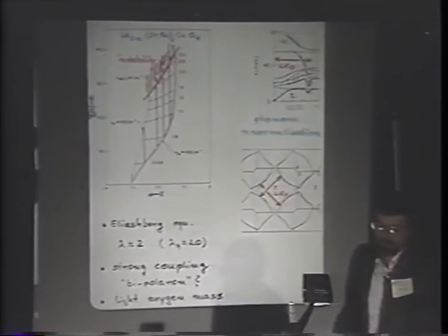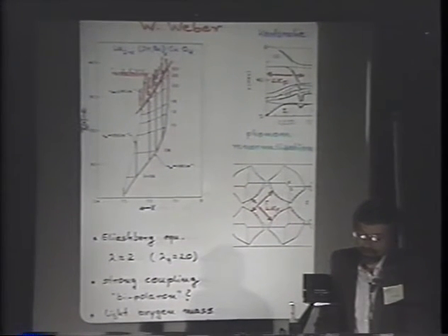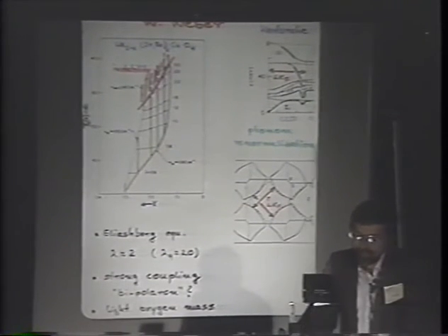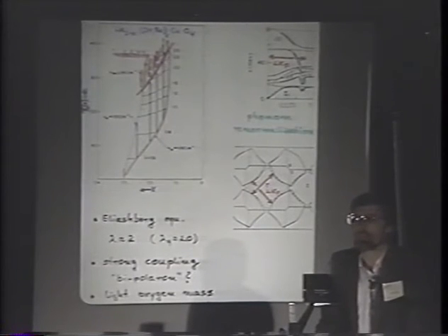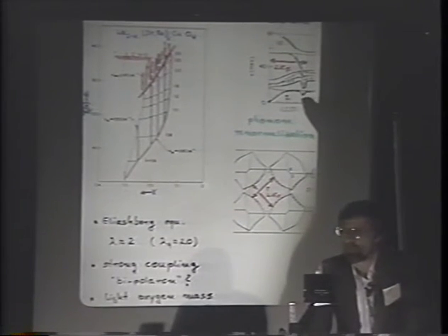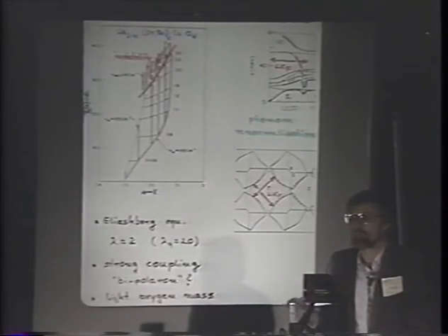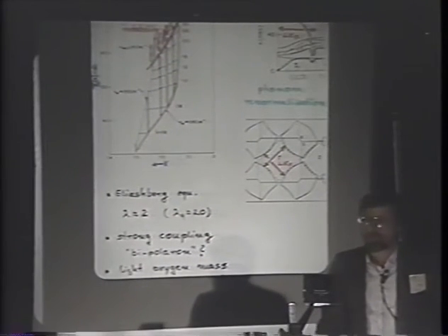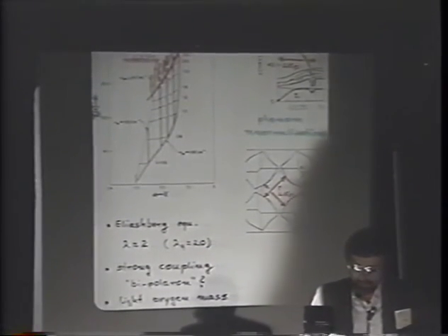Weber is calculating at the moment the electron-phonon coupling in the 90-degree materials, and we'll see what happens. However, he has also realized that he is at the limit of what this theory can really support. The soft phonons that occur here have line widths, have lifetimes which are comparable to their frequencies. So the whole concept may become somewhat questionable, and maybe one has to go into a more strong coupling limit or bipolaron limit.